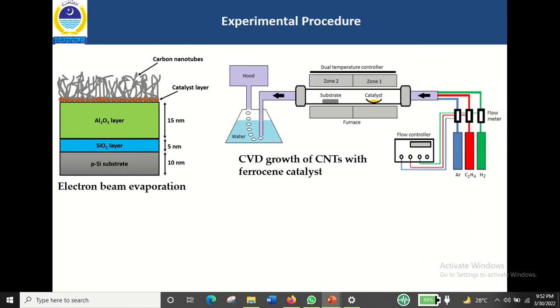So here is the procedure adopted to complete this research. First, we prepare the carbon nanotubes in the laboratory rather than buying commercial ones because they have different parameters and structural properties. We prepare the carbon nanotubes by ourselves with the desired structures. We use a substrate for the growth of the carbon nanotube forest.